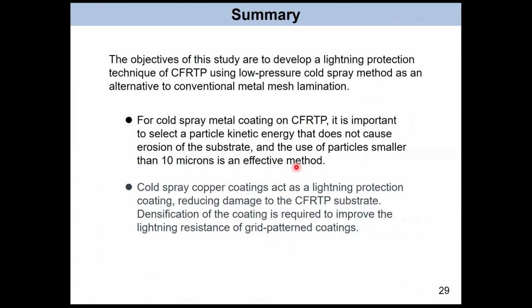So let me summarize my presentation. The objective of this study was to develop a lightning protection technique for CFRTP using the low pressure cold spray method as an alternative to conventional metal mesh lamination. For cold spray metal coating on CFRTP, it is important to select a particle kinetic energy that does not cause erosion of the substrate, and using particles smaller than 10 micron is an effective method. Also, cold spray copper coating acts as a lightning protection coating, reducing damage to the CFRTP substrate. Densification of the coating is required to improve the coating property for lightning strike.